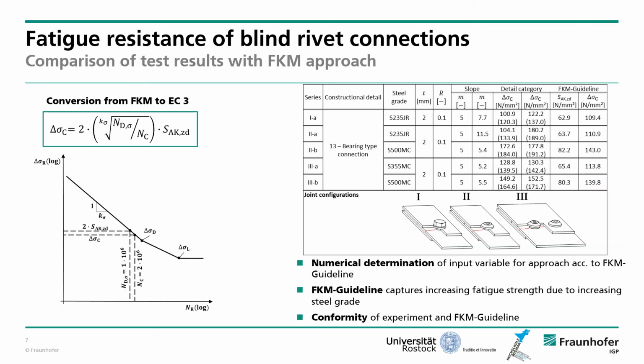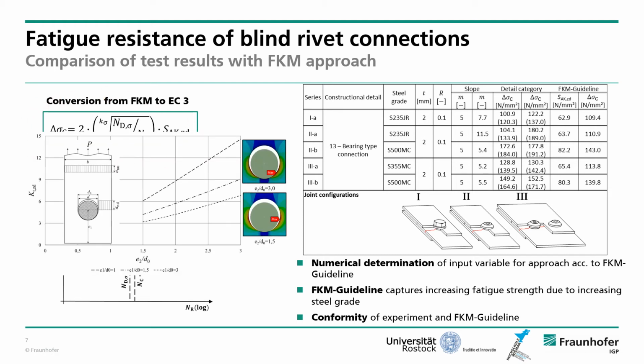For the further evaluation of the results, the approach according to the FKM guideline was used. This FKM guideline allows to determine the fatigue resistance of a construction or a component with a synthetic Wöhler line approach. And this value from the FKM guideline can be converted into a detail category according to the Eurocode 3 by this shown equation. And for this approach, according to the FKM guideline, some input parameters are required.